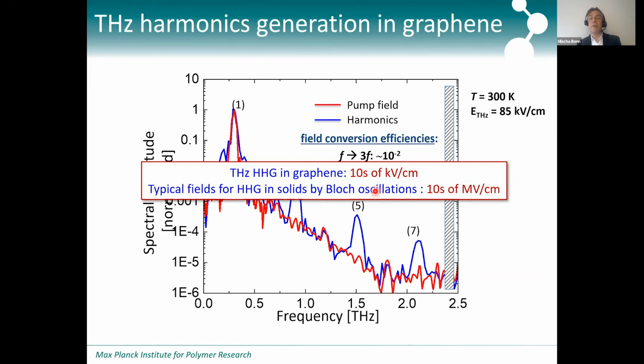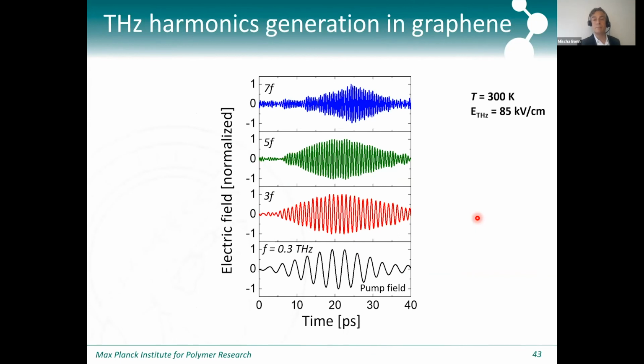And so if you compare the fields that we need to generate higher harmonics, it's tens of kilovolt per centimeter, to the typical high harmonic generation that you need from Bloch oscillations, that's several orders of magnitude higher. So the effective nonlinear susceptibility of this material is immense.